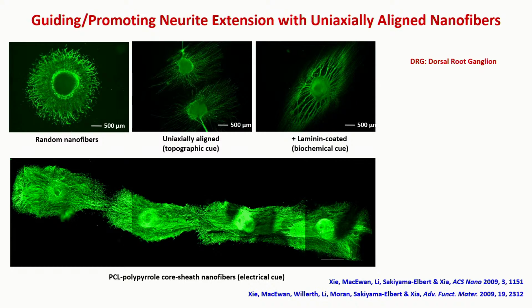And these nanofibers are pretty ideal to guide the extension of neurites. We use this particular model system of dorsal root ganglia isolated from chick. So you can just culture them on these nanofibers. If the nanofiber has a random orientation, the neurites are going to be projected into all different directions. There's no preferential orientation for these neurites. However, if you culture them on uniaxially aligned fibers, which I showed on the previous slide, the newly formed neurites will be extended along the fiber direction. The fiber is aligned in this direction. So you see the physical guidance from the nanofibers.